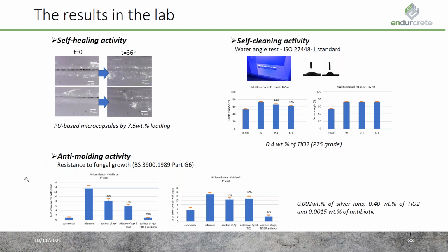And finally, regarding the anti-molding activity, antifungal activity, this was measured according to the resistance to fungal growth test. The relevant factors in the formulation can be seen on the right bottom of the slide. We had 0.002 weight percentage of silver ions, 0.4 of titanium dioxide, 0.0015 of an antibiotic, and 0.4 titanium dioxide of P25 grade. And the formulation reached category 1. That means that we had less than 1% of the area covered with algae after 4 weeks of visible radiation, as you can see in this graph. And on the other hand, we had also very good antifungal activity in the absence of light.